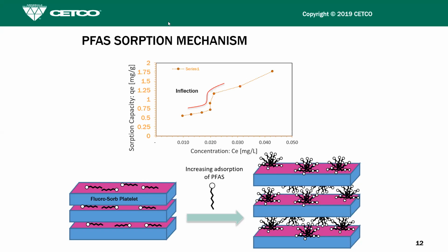Now, whenever we bring this subject up, there's often a concern that that is a swell mechanism. It sounds like swell, but it's not. This is happening on the micro scale, and we now have full-scale drinking water and groundwater ex situ pump and treat sites where we're seeing no swell. But this phenomenon of the platelets expanding and allowing more product to get in gives us a superior absorption capacity. And again, we also have less effect from competitive absorption.